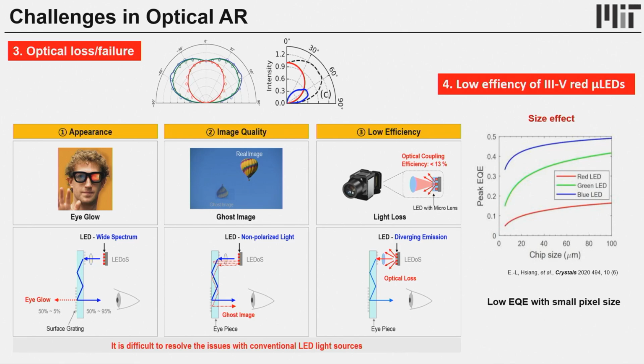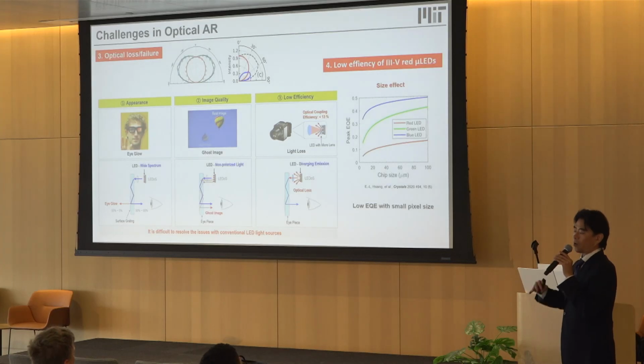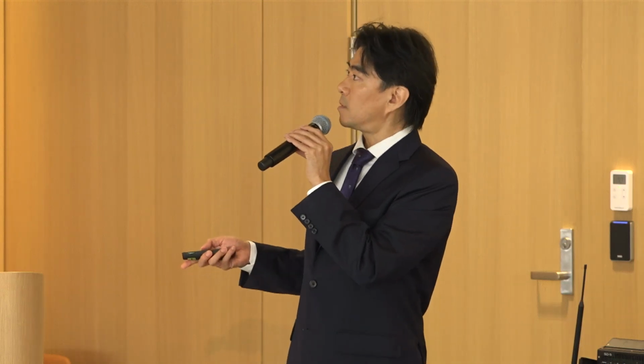At the same time, red is problematic. Red micro LED is problematic. Typically, green and blue can be made out of gallium nitride, III-nitride materials, but III-V is needed to do the red at the moment. If you scale it down to less than 10 micron, the EQE drop is substantial. So you really need to find a solution to address this. These are the outstanding challenges out there. If you know how to address this, then you can really revolutionize AR in the future. I don't know if it's an exaggeration, but we believe this is the only way to go.